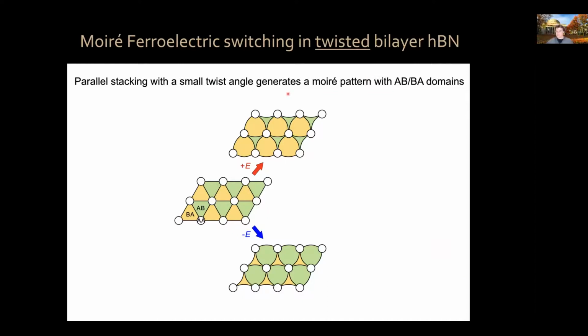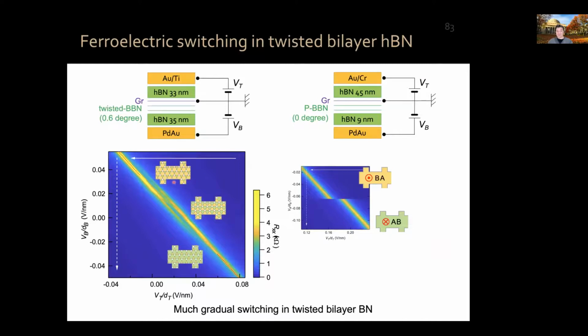If we have a small twist angle between the 2 layers of hexagonal boron nitride, now we have these BA and AB type of domains, similar to magic angle graphene. Now, these domains have different energy configuration and different electric dipole moment. So when you apply an external electric field, if it is of one type, you will increase the size of one of the types of domains. If you have another type, you will decrease the size of the other domain. And in fact, if we realize twisted bilayer boron nitride, in this case 0.6 degrees, and we make a similar ferroelectric field effect transistor, we can see that at a given electric field, one type of domain configuration is dominant, and then slowly we switch towards the other type of domain configuration. This is in contrast to when we have parallel stacking of the two boron nitride layers, where the switch is abrupt. You can see here the gradual transition from one domain type to the other domain type.